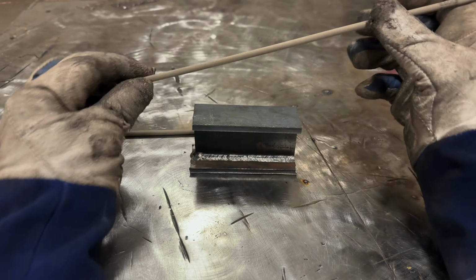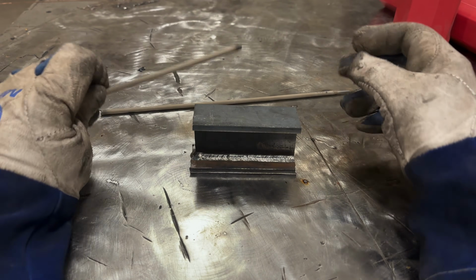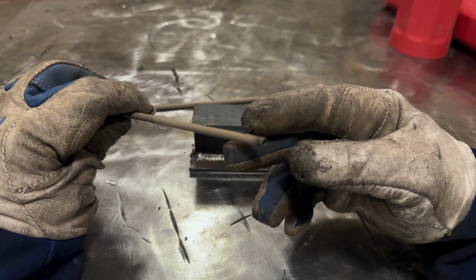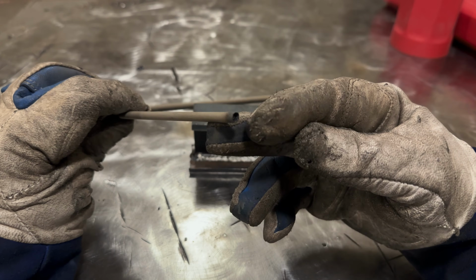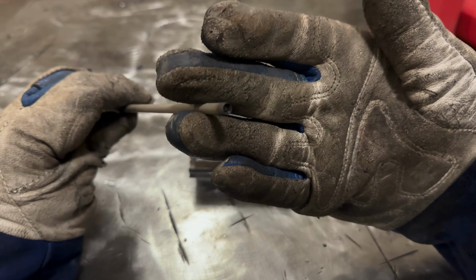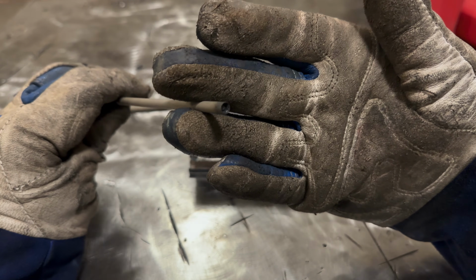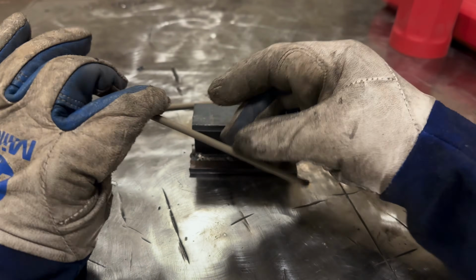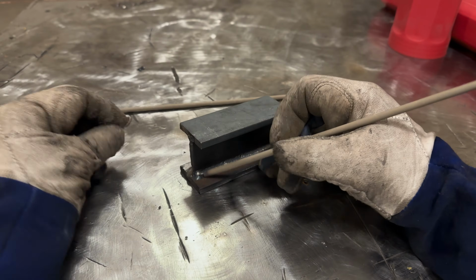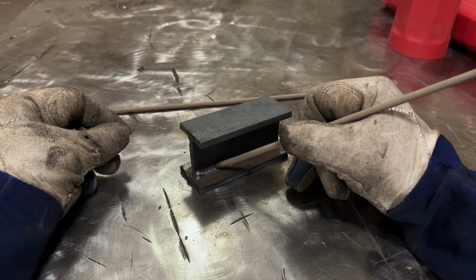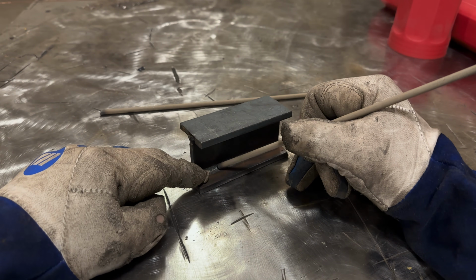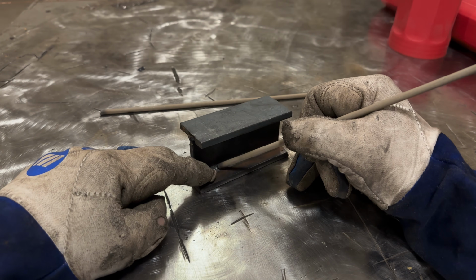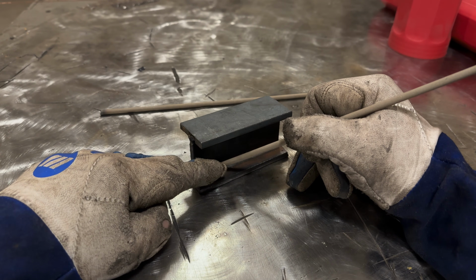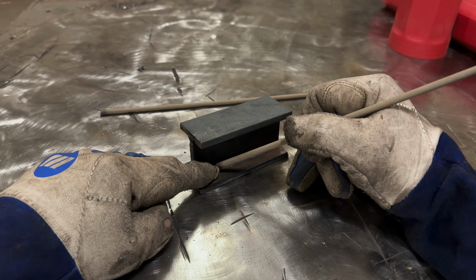I find that 6013 is a very easy rod to get arc blow with, because if you look at how recessed that is, this flux, it's very easy while you're welding and you're just going along, to not realize how long your arc gap actually is, because that tip is burning off further up the rod than the flux is.